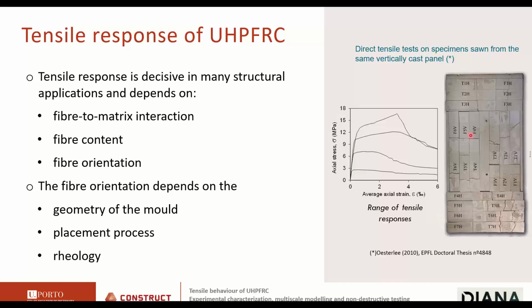So here, this is a vertically cast panel from which several specimens were sawn to test under uniaxial tension. And you see here the range of responses that was obtained. This is described in the doctoral thesis of Oesterlee from the EPFL. So the same material, same theoretical fiber content, and a very large range of tensile responses in the same panel.